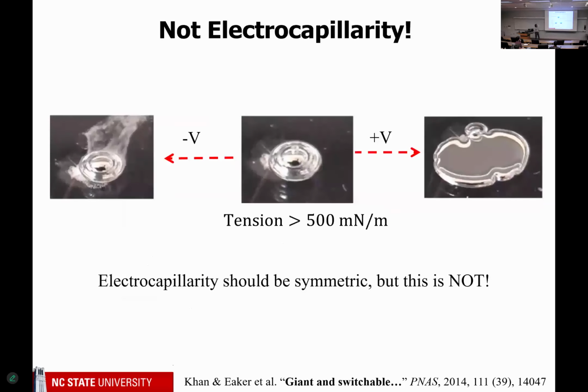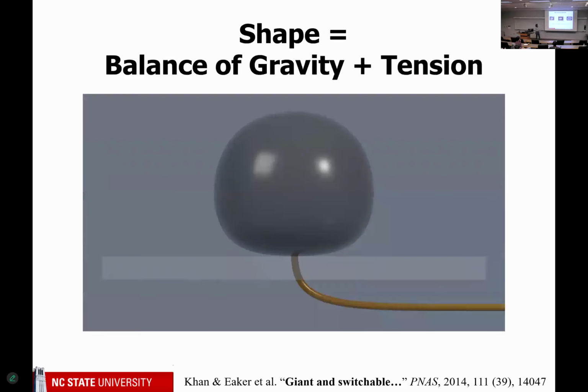And so for a number of reasons, I just told you a whole story, and now I'm going to tell you it's not electrocapillarity. Because when we apply negative voltage, actually the metal beads up and we see bubbles form on the surface. But when we oxidize the metal, it spreads. So it's not electrocapillarity. And so we made our own electrocapillary curve. So we take a droplet of the metal and we stick a little electrode into the bottom so we can apply a voltage to it. And we are able to measure the surface tension based on the shape of the drop. So if the tension's really high, it will look round like you can see here.